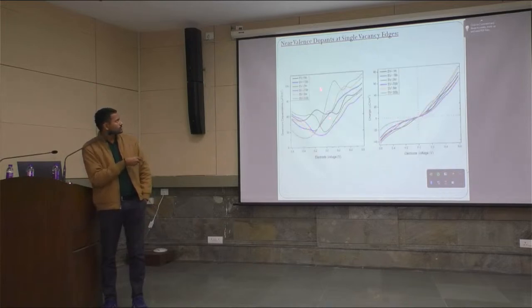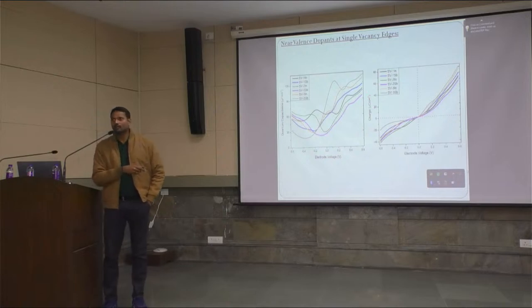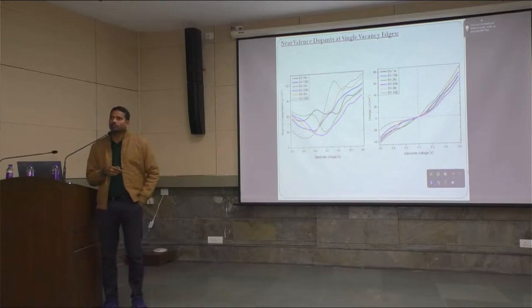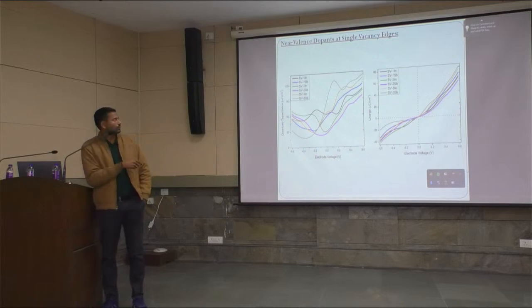And all these indium and antimony dopants are offering the quantum capacitance on the positive side of the electrochemical window. This says all these dopant structures are suitable for the anode electrode of the asymmetric supercapacitor rather than the symmetric supercapacitor, because the quantum capacitance peaks are observed on one side only. So we can say that these are suitable for the anode of an asymmetric supercapacitor.